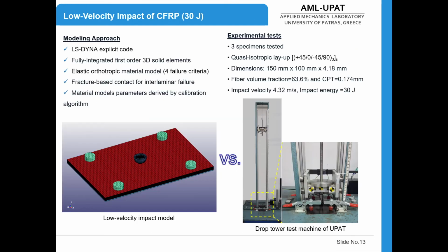Now, let's try to recall why we have made all this calibration of the material model. The idea behind is that we are trying to use this calibrated data in order to simulate the impact test, and we believe that using this kind of calibrated data, the simulation will be very close to reality. So what have we done first? We have done low velocity impact tests on CFRP laminates made by the same material as the one that we have already calibrated.